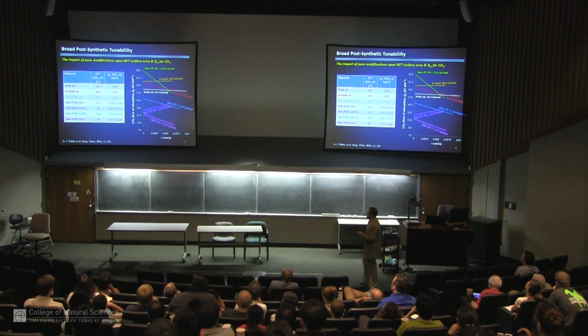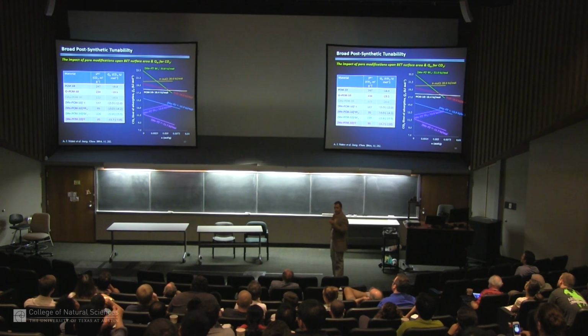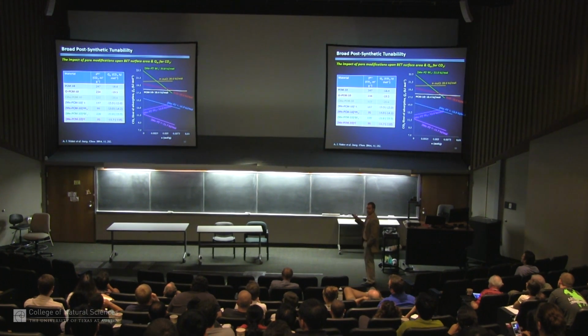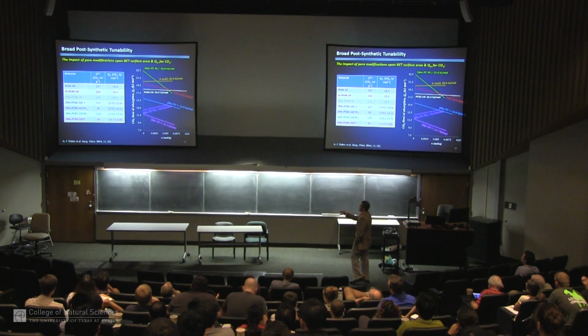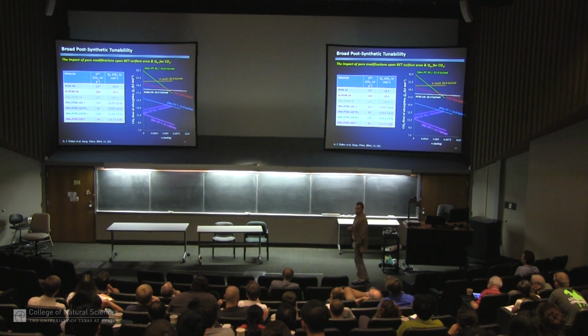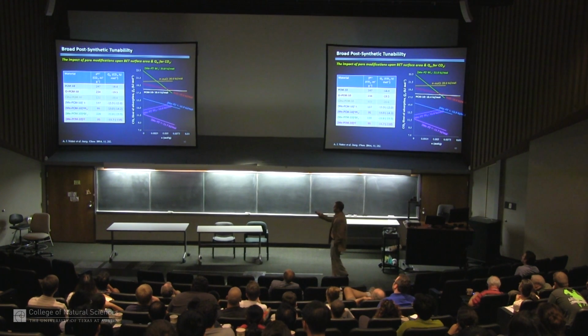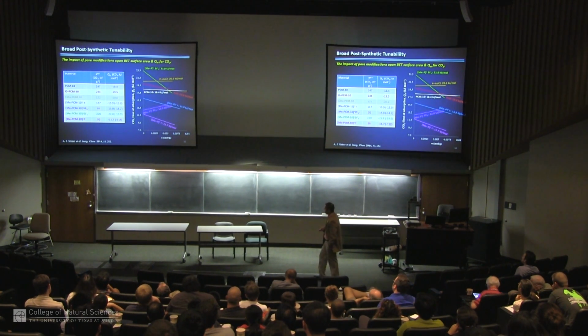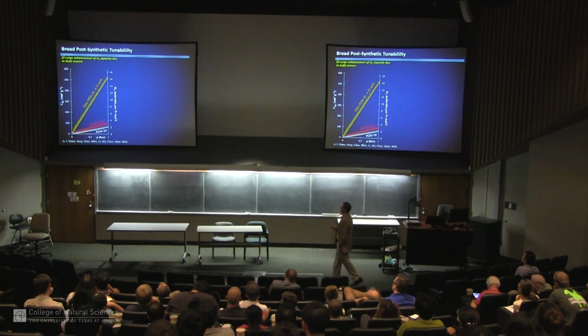And we study these carefully to see how the properties of the materials change as a result of what is inside the pore. And so one good example, as I told you, CO2 sequestration. We look at the binding energies of CO2 in the materials. So we're interested in how the CO2 molecules are interacting with the inner surfaces of the pores and which types of groups are more useful. So here, this is the parent material, the white data. And by adding different groups to the pores, we can tune positively or negatively the average binding energy of CO2. And that's good because if you want low capacity but easy regeneration, you want to be down here, low binding energy. If you want high capacity in which the CO2 is more strongly stored, you want to be up here. And so we can tune pretty broadly just by doing one simple post-synthetic adaptation.